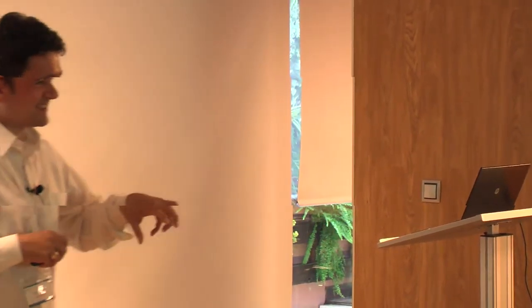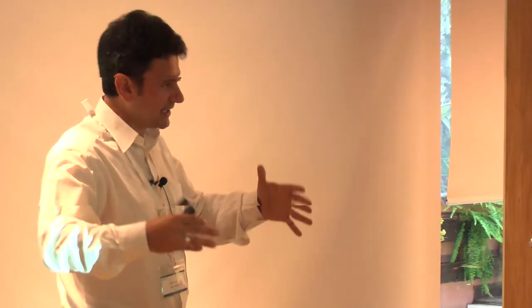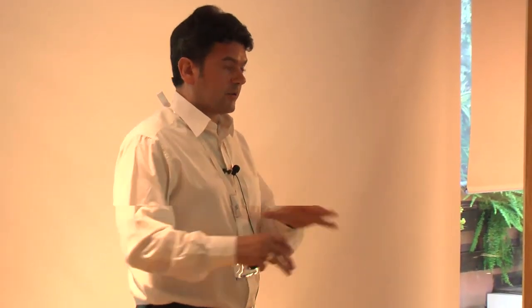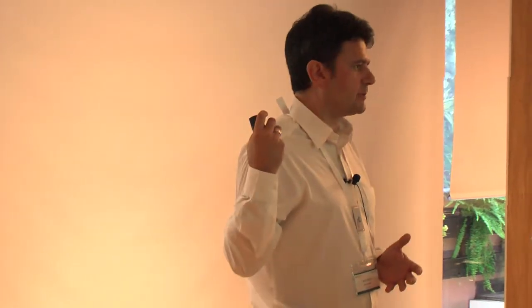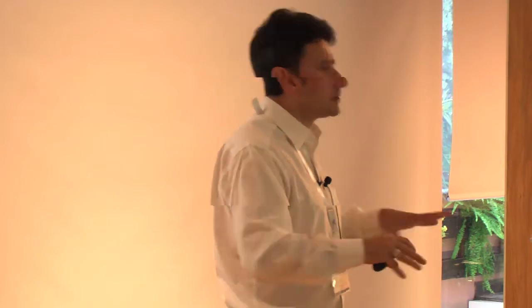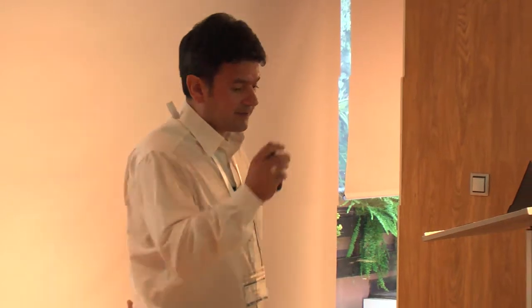Finally, when you have the models for the major degradation mechanisms that are occurring at the same time, then you can bring everything together. But if you look at this aging for the entire device, it's not only a black box, but it's a box of Pandora, because there are a multitude of mechanisms that are occurring, and then perhaps it's possible to get an Arrhenius analysis and to get an effective activation energy. But what does it mean? So now we tried the opposite way, just from a scientific point of view. Can we understand the specific failure mechanisms? What is the activation energy? And then at the end come to the entire device.